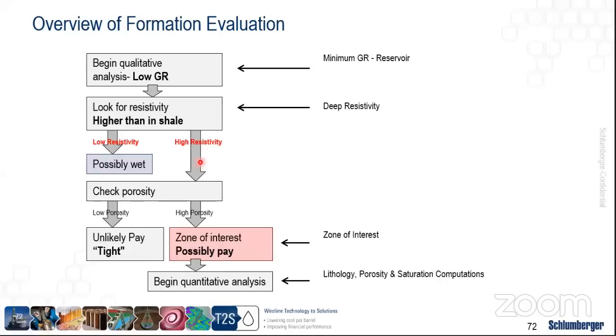In order to identify this, we need to check the porosity. If we have a low porosity, it's likely to be tight, which is not a pay zone. And if it has a high porosity, then this high resistivity is coming as a result of a very resistive fluid, and this is a possible pay zone.